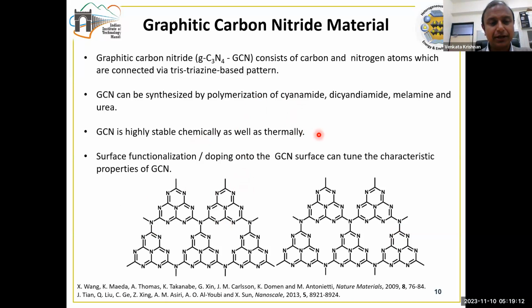Furthermore, this graphitic carbon nitride is also amenable to surface functionalization and doping, which can tune the properties of this material. So we can functionalize it with sulfonyl groups or nitrile groups or even phosphoryl groups, or you can dope it with heteroatoms such as boron in order to tune the acidic and basic properties of this material.